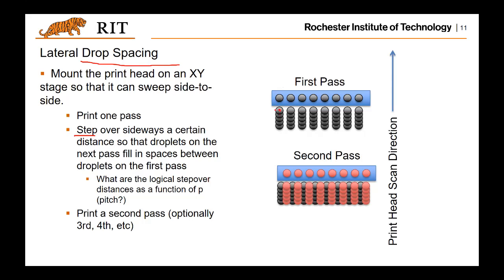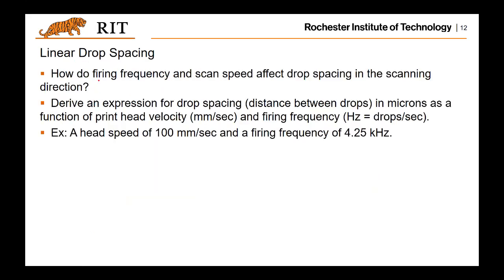So basically, if we measure the distance between the two droplets, it is affected by both the firing frequency, that is how frequently the nozzle generates and sends out a droplet, and also the scan speed, that is the motion of the printing head. Both will affect the droplet spacing in the scanning direction, and that will be a function of the printing head velocity and the firing frequency.